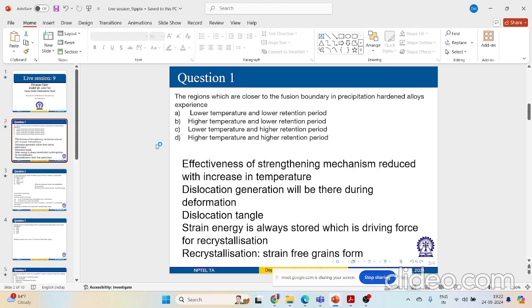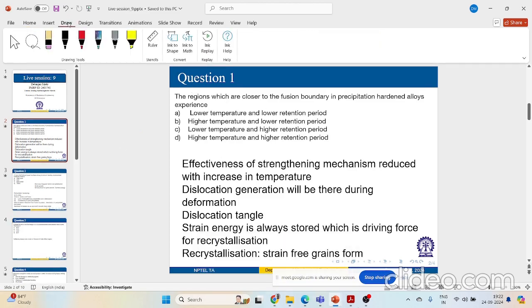My first question asks: the regions which are closer to the fusion boundary in precipitation hardened alloy will experience what? This is fusion boundary, right? And this is heat affected region. As you are closer to your fusion boundary, you will have lower temperature, lower retention period, or higher temperature, higher retention period, or higher temperature, lower retention period, or lower temperature, higher retention period. We have discussed it right now. So more towards fusion boundary, we will have higher temperature and higher retention period.